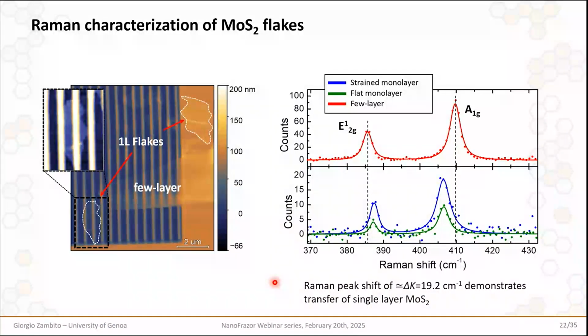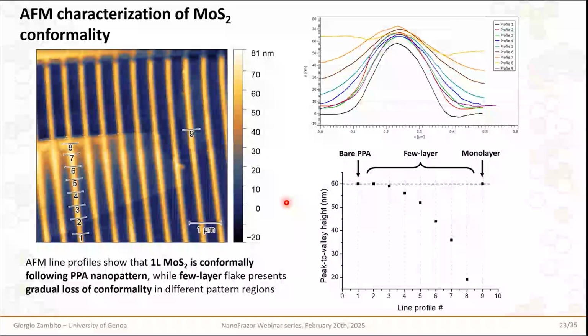I told you that they are more or less conformal, but can we actually quantify the degree of conformality? Well, to this purpose, we plotted different line profiles extracted from different positions along the AFM topography image, and we compared these profiles with the profile obtained from a bare PPA after patterning with grayscale lithography. We observed that the same peak-to-valley height that we observe on bare PPA is reproduced again in the lowest part of the few-layer flake and also on the monolayer flake, which is here. The few-layer flake is also interesting in this image because it has a decreasing degree of conformality when we go from the bottom to the top part of the image. And as we will see, this is interesting for different reasons.